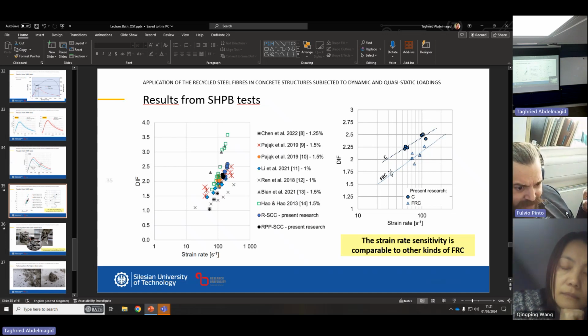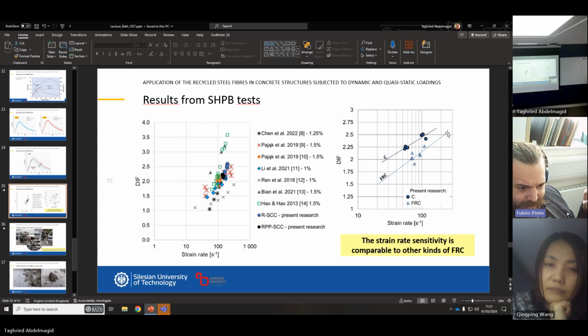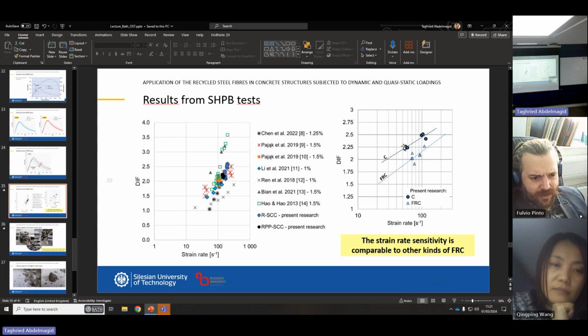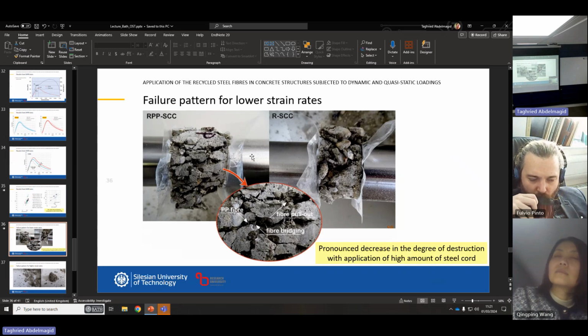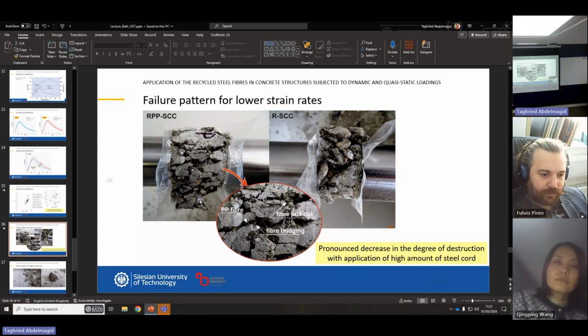Or it seems that the gradient of the light blue curve is higher. Yes, but you can see there are only few results here. You need to have more to see. But generally, all types of fibers cause the decrease. Of course, for the lower strain rates, you can see that the level of destruction is lower and so on. This is the only thing that we can be sure of. The other parts, how they really influence, how the stress on the tip is changing and so on, we can discuss on the quasi-static tests. We can do it, but on the dynamic, it's impossible.